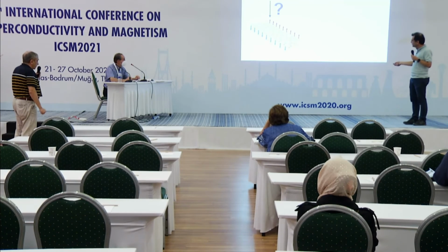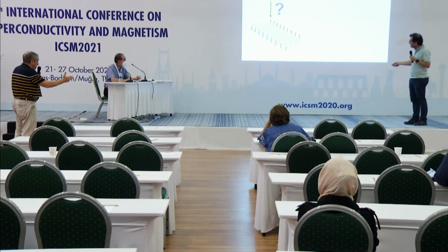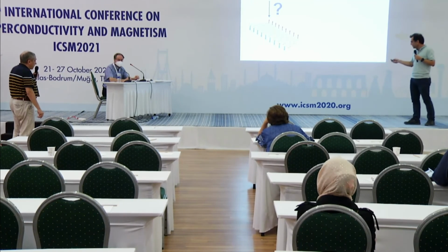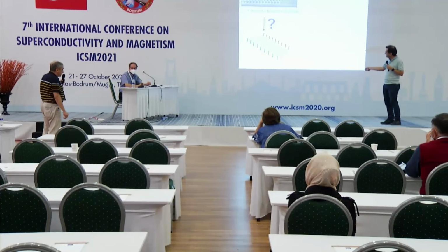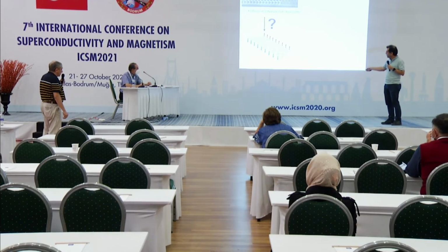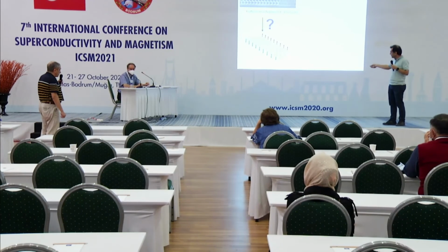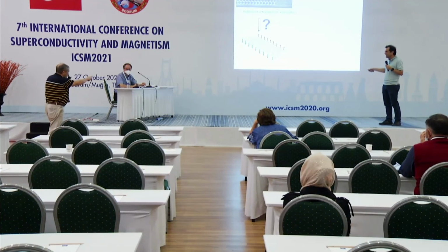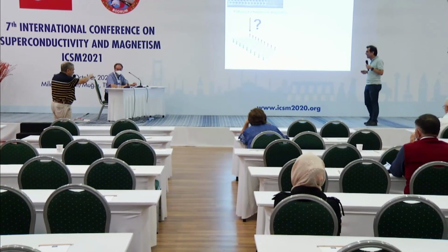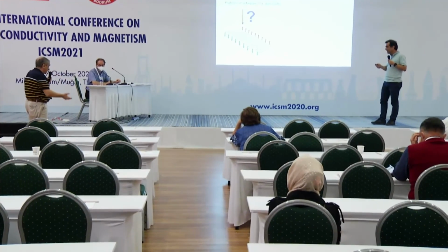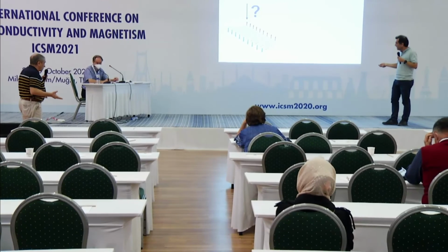Well, actually, in any DFT calculations, if you look at the pair correlations, spin correlations are ferromagnetic along the edge. It's also a theorem. You fix one down electron here, then all these electrons will be down, and all these electrons will be up. So there is antiferromagnetic order. Because of what? No, this arrow should be 0. The spin density should be precisely 0. It's the Wigner-Eckart theorem, and there is no contradiction.